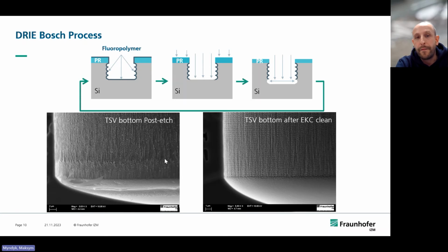But after etching of TSVs, the walls of the TSVs are covered by this fluoropolymer passivation layer, from the top to the bottom. This layer is there to protect the walls from the isotropic etch, to get these nicely etched vias. But after etching, the polymers need to be removed. And why do they need to be removed?